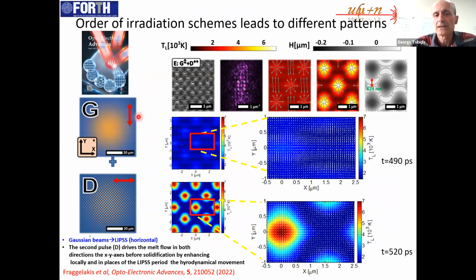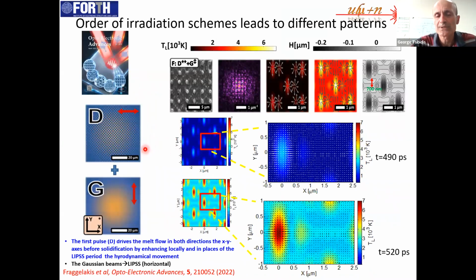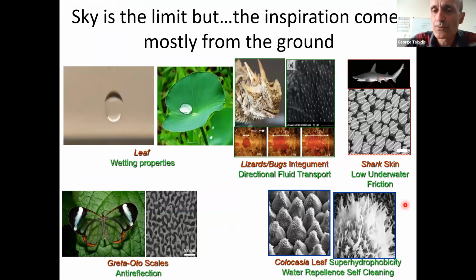And we produce even bigger complexity. I mean, we increase the complexity of the topography by using a combination of Gaussian beam and DLIP separated temporally from each other. And of course, we change the order of irradiation, and we saw that we ended up with different structures. So it is a combination of excitation of the material and also fluid dynamics behavior that explains the formation of these structures. So we have managed through this scheme to produce these periodic, biomimetic structures.